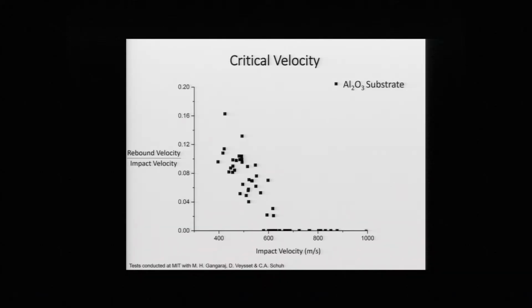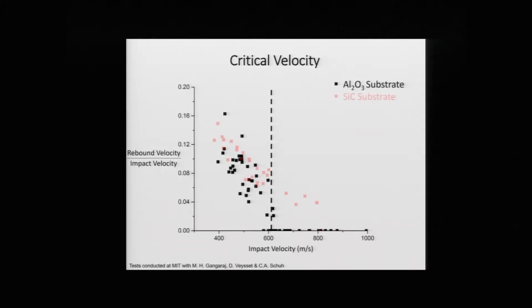And what you'll see is that on this coefficient of restitution graph, these will appear as points on the x-axis. And you could see that at around 600 meters per second, you'll get adhesion. But these are the results for titanium deposited on aluminum oxide. What happens when we deposit on silicon carbide? In fact, what we observed was that the critical velocity is closer to 800 meters per second. So changing the ceramic has a significant influence on the velocity you need to be spraying these at.